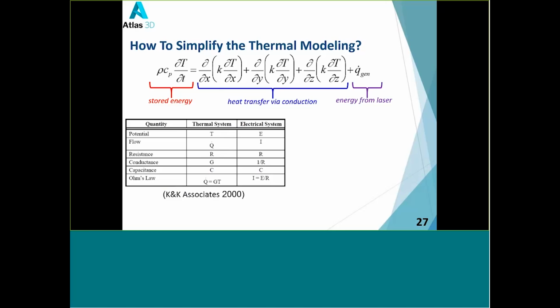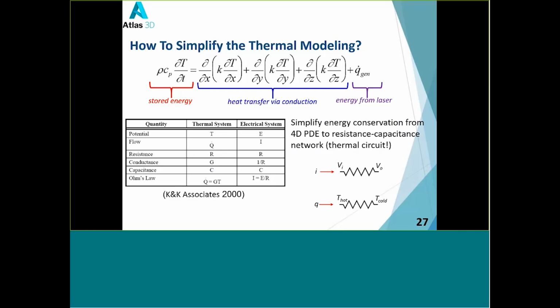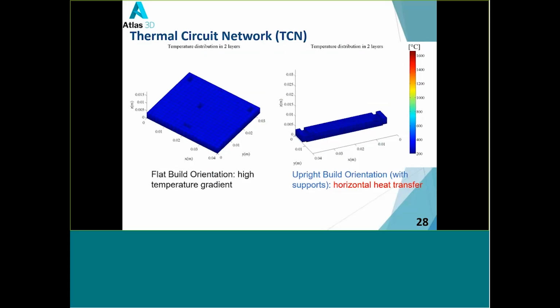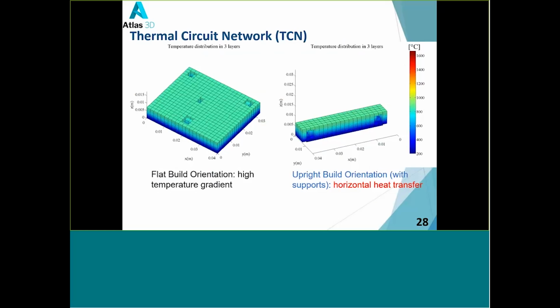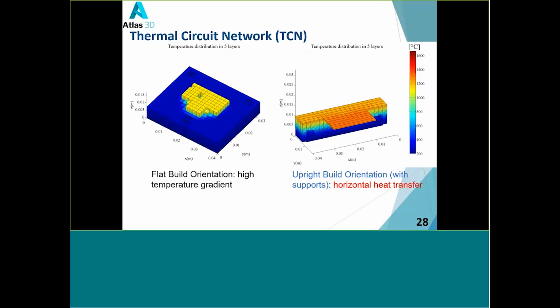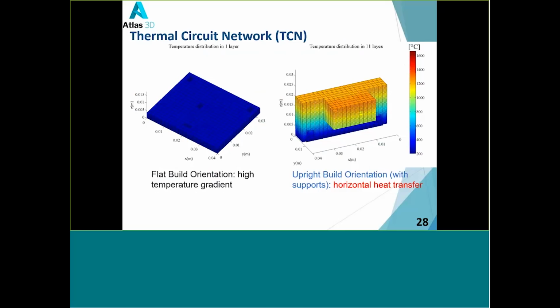And we know that the thermal system and the electrical system have some similarities. So a good idea is that we model the heat transfer in the same way we model the electric current, so that we can simplify the 4D PDE of the heat transfer into a network of thermal resistance and capacitance. And we did that, and we can model the heat transfer when we build this part both horizontally and vertically. You can see that when we build the part horizontally, the thermal gradient is larger because the cross-sectional area is larger and the heat transfer is faster.